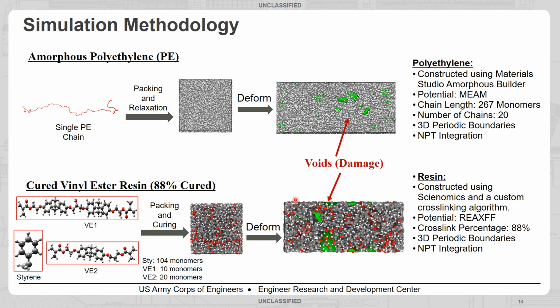But here, for some current work that we're doing, we are comparing deformation of amorphous polyethylene to a vinyl ester resin. So we have a thermoplastic compared to a thermoset, and we want to compare and contrast how damage progresses in each system. Both of these systems are made differently, right? One is an amorphous polymer, so we pack the chains randomly into a box. For the vinyl ester resin, we have different monomers added to a box, and then we have a curing algorithm that selectively cross-links them until we reach a desired curing percentage. Then we equilibrate the box at high temperature and anneal it, which is standard in MD, and then we deform them.